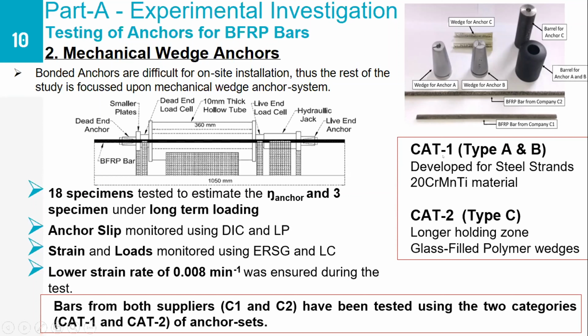So these pictures are showing the different types of anchors that have been used. So basically the category type 1 or the cat 1 anchor has two different sizes for 8 mm and 12 mm diameter, which have been designated as type A and type B here. And the category 2 anchor, which has a longer holding zone, and it has a glass filled polymer wedge, has been used for also testing these 8 mm diameter BFRP bars. This second type of anchors is only provided for stressing of 8 mm diameter bars. So only the 8 mm BFRP bars provided by the C1 and C2 suppliers have been tested using this category 2 or cat 2 anchors.